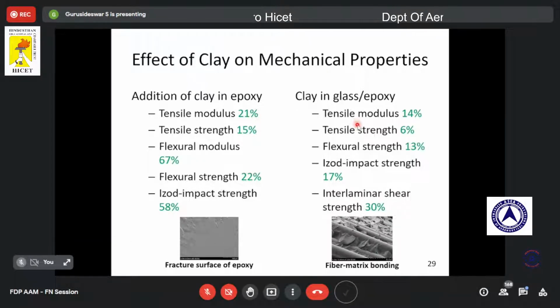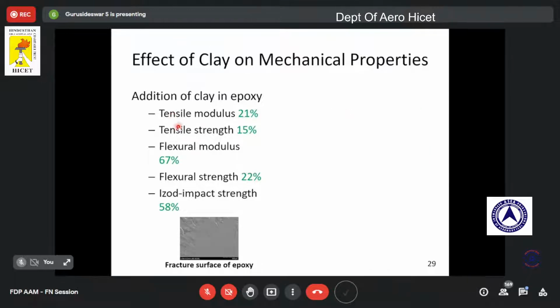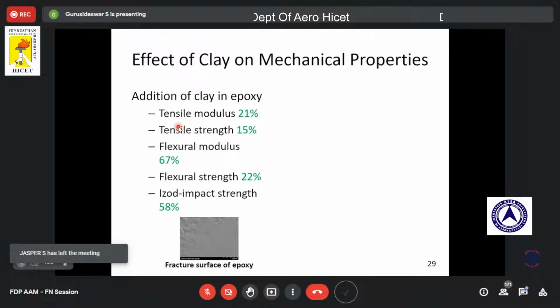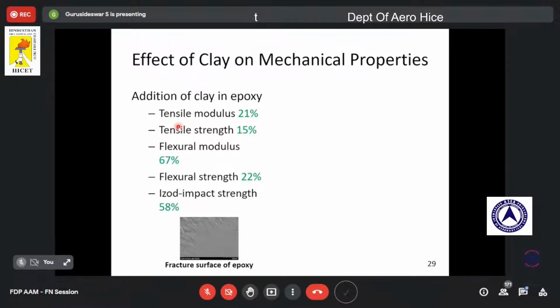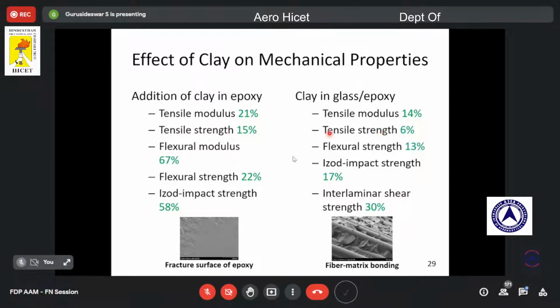And also we wanted to understand the effect of clay in glass epoxy. As I mentioned in my previous slides, in the whole talk we use two materials. One is polymer nanocomposites, where we disperse the clay in epoxy and understand its mechanical performance. And the second one, we wanted to understand the effect of clay in a traditional composite. You know a composite, right? FRP is the composite where the fiber is the major reinforcement, the primary reinforcement, and the polymer is the matrix. So in a traditional composite material, we have added that nanoclay, and also found a good improvement. Here I have listed the improvement of mechanical properties when we disperse clay in glass epoxy composite.